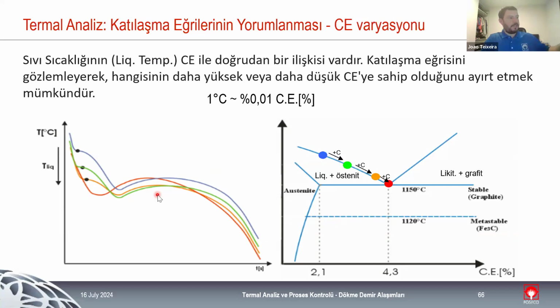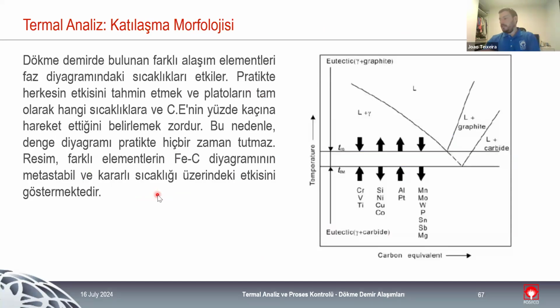And this is just to show that this is really important, especially for production, when you are moving a ladle from one side to the other to pour it into the sand molds. Each degree that we lose in temperature, it's 0.01% carbon equivalent. So we are losing carbon each time the temperature drops. So we need to also control really, really carefully the temperature when we are producing. This is, again, just for us to know the different elements and the effect that they have.